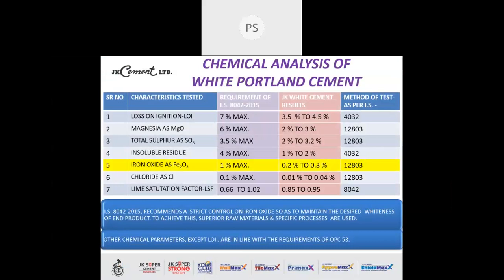Now we look at point number 1, LOI 7% max, we get a range of 3.5 to 4.5. Magnesia 6% max, we get a range of 2 to 3%. SO3 content 3.5% max, we get a range of 2 to 3.2%. Insoluble residue IR, 4% max, we get a range of 1 to 2%. Iron oxide we have already seen. Point number 6 is the chloride, 0.1% max. JK cement has a range of 0.01 to 0.04%. And last is the LSF, lime saturation factor. It should be between 0.66 to 1.02. We have a range of 0.85 to 0.95.